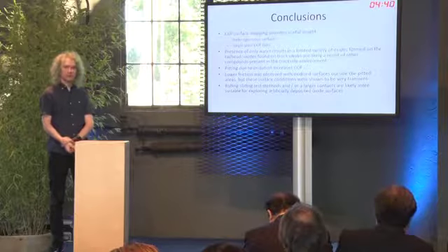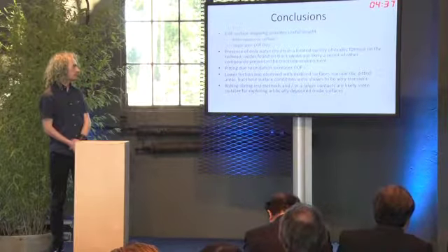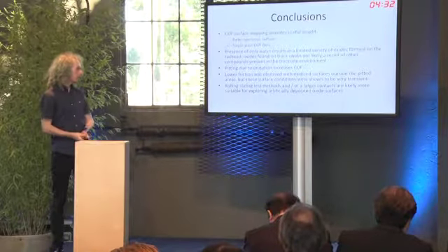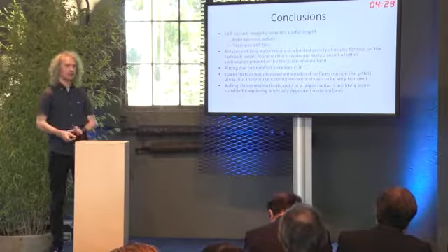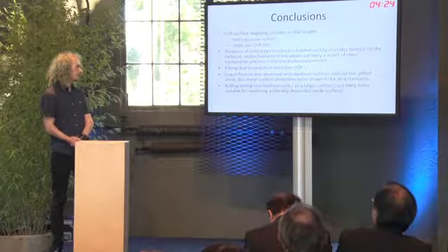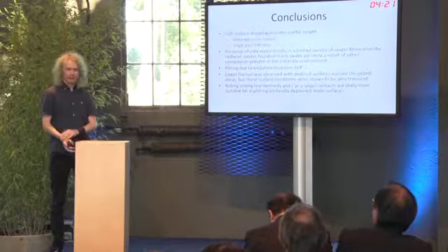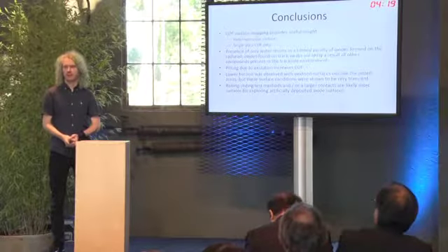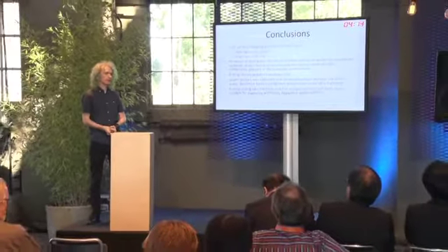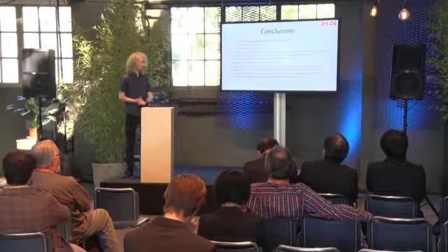Through looking at these coefficients of friction maps, we found that pitting due to the oxidation increases the coefficient of friction. However, lower friction was observed within these heavily oxidized samples, but outside of the areas which we found are heavily pitted. And finally, looking at the methods for testing the individual oxides, we believe that there are better methods for doing this. So we will be testing it on larger contacts, for instance, a full-scale contact, but also using a larger sample or doing a rolling sliding test.